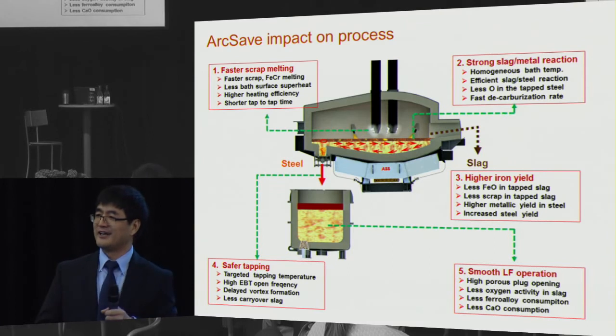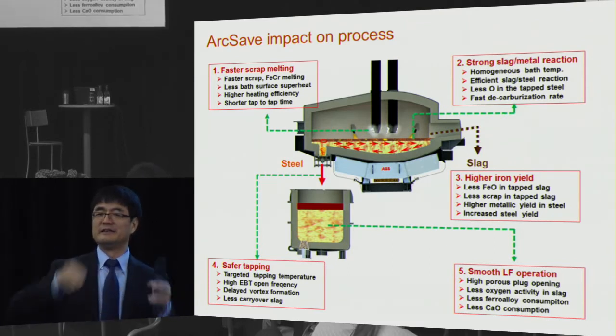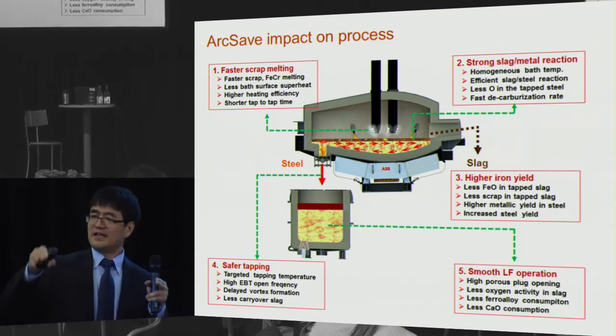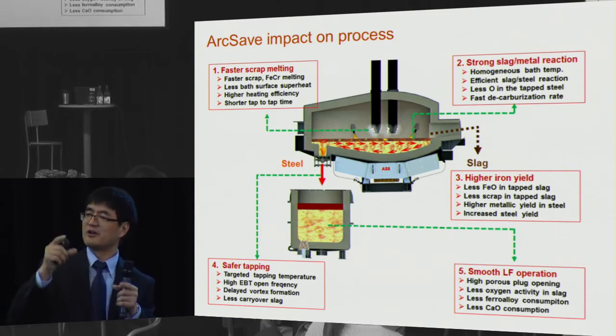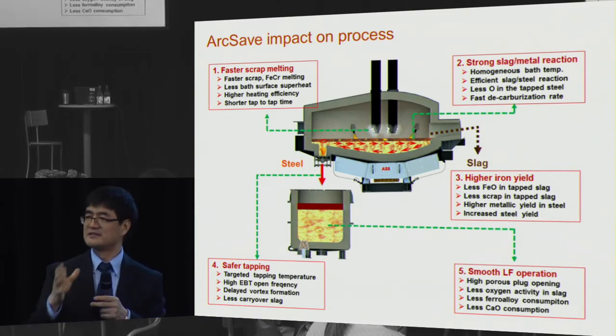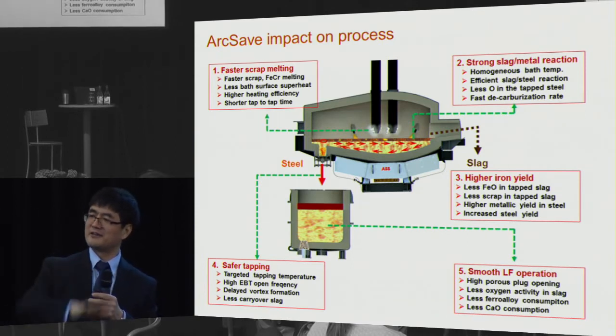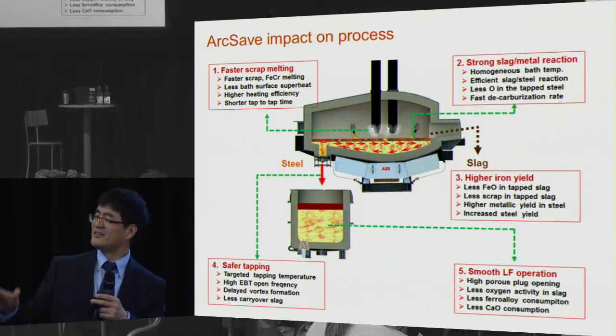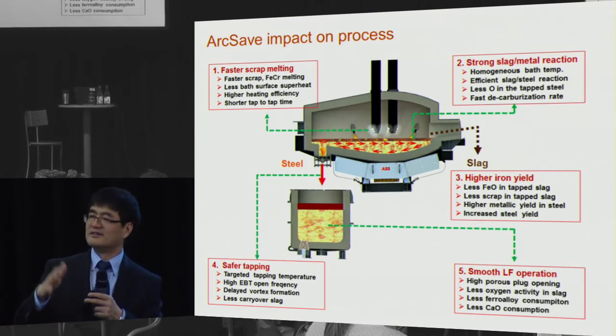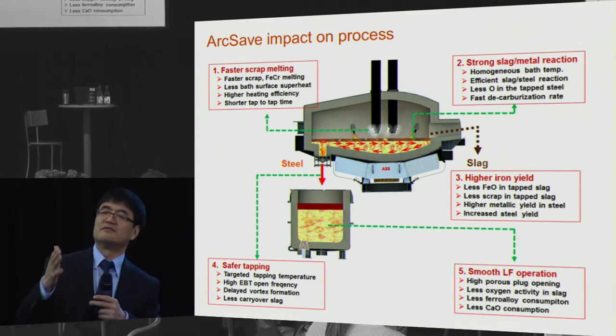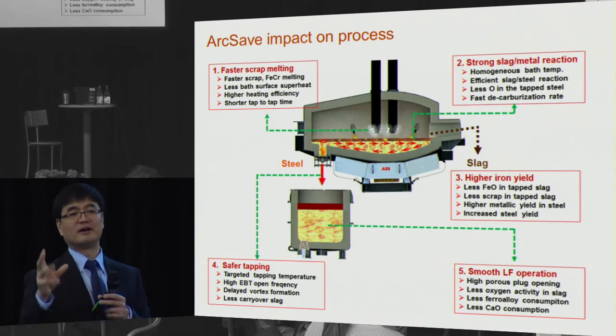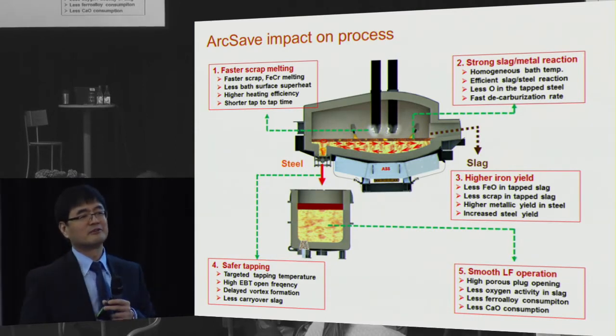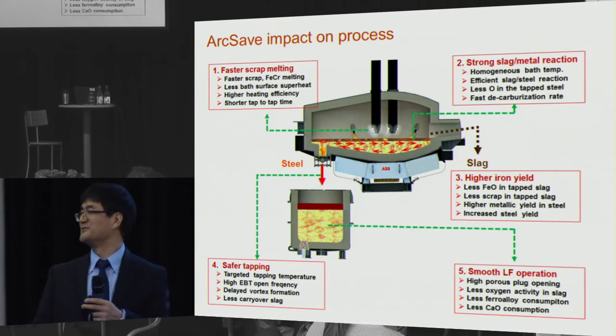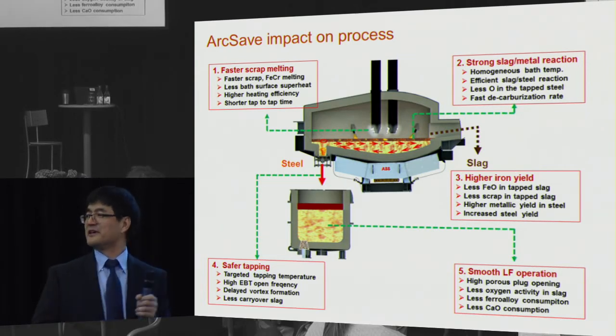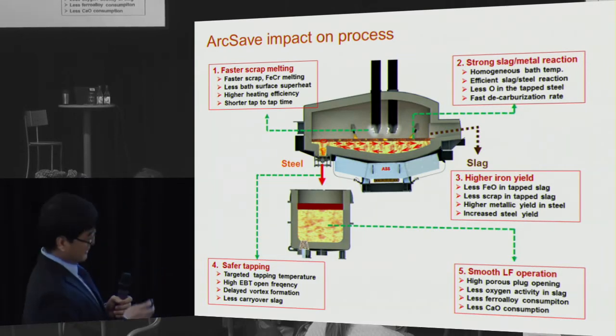The third one is that the yield of the iron is quite high. As we know, when we tap the slag, we have lots of steel droplets in the slag. Because of the magnetic field, that is reduced by half. That means with 50,000 tons per month production, you will save around 400 tons of steel, which is a big saving from the economic point of view.